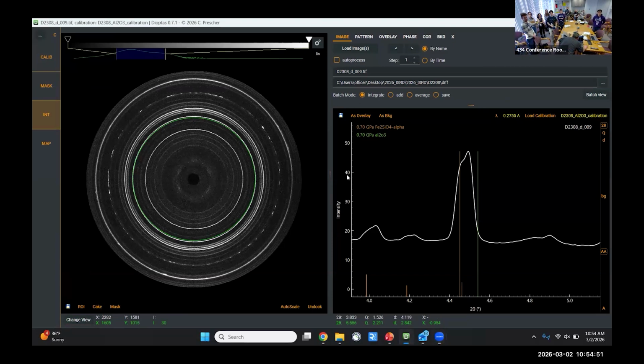Yeah, okay, that worked. You see this line here, you see at the top, this green line is a perfect circle. But you see at the top, it's not a perfect circle anymore. It's an ellipse now because we're squishing it more in the vertical direction. So it doesn't change by a huge amount, but it'll change a little bit. So we see our ellipse, but now if we go back to the cake pattern, remember when we unwrapped this thing when there was no differential stress, and we just got a perfect circle because all of the planes are squished an equal amount in all directions, but now they're squished more in the vertical direction.